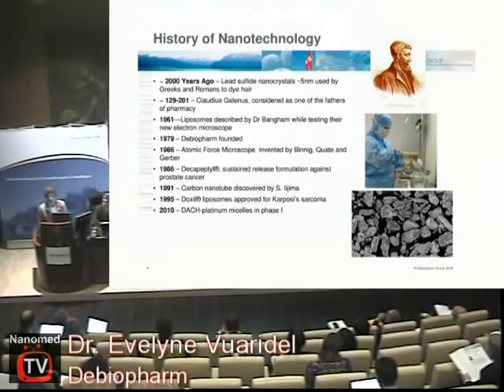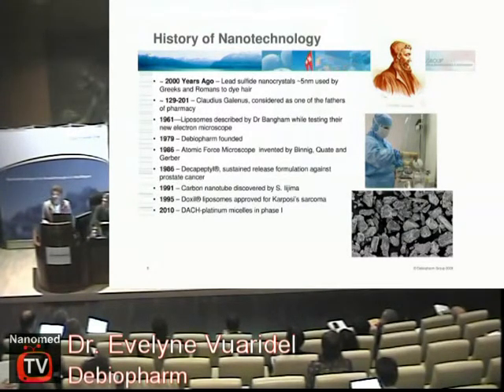I put my company in between those milestones. We are now doing clinical trials with a platinum derivative using nanotechnology. We are moving to nanotechnology because we worked for many years with microtechnology — those particles are about 30 to 50 micrometers in size. But size is very important, as we heard today. During manufacturing you must always achieve the same size and the same distribution, because if the size varies, the release of the active compound will differ.